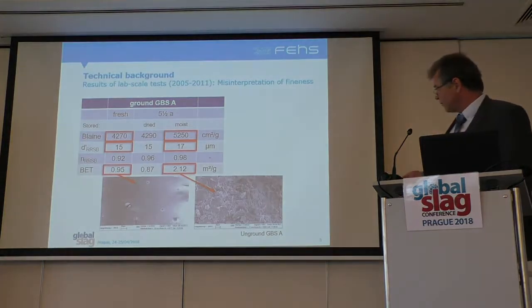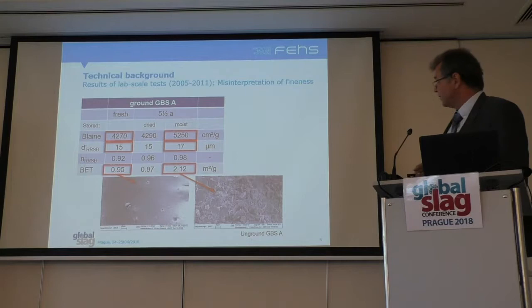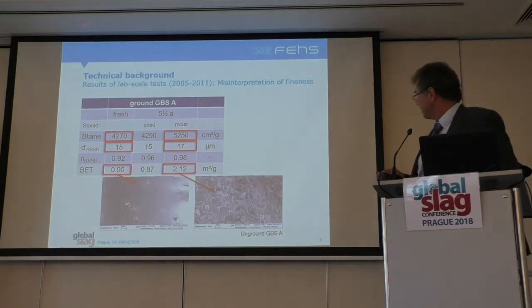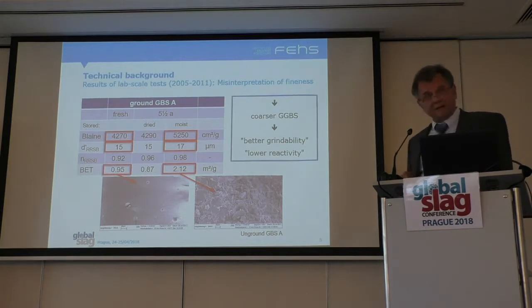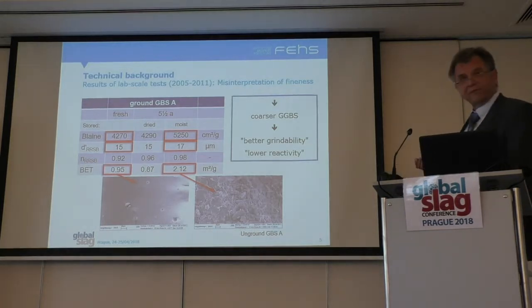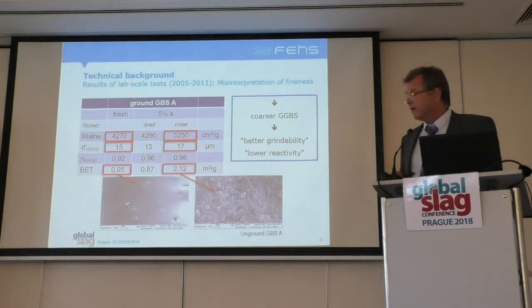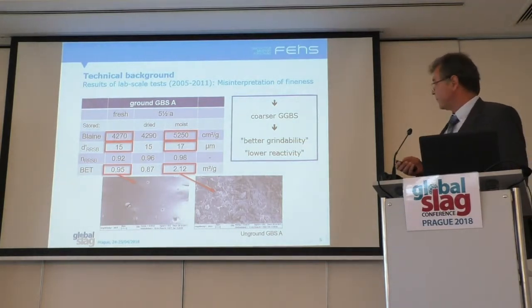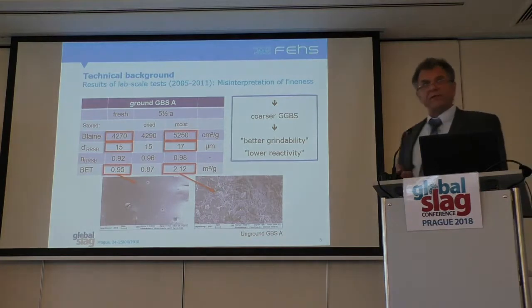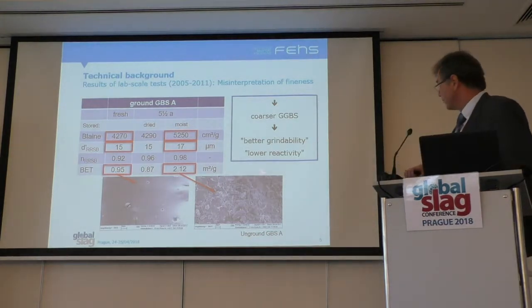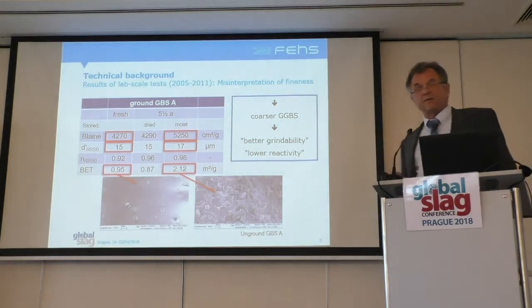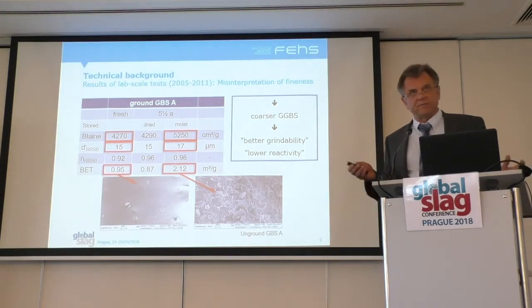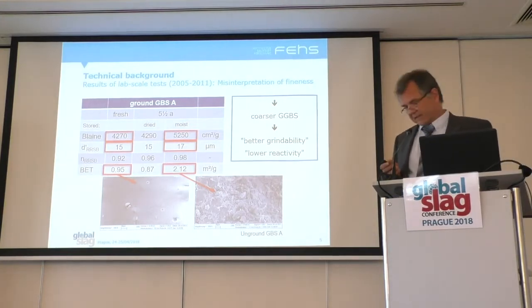That's a picture of the surfaces of unground slag: very smooth for fresh slag, and a reacted surface for the moist stored slag. The result is a misinterpretation of fineness. That means the slag, if it is ground GBS, is coarser than normal, than expected. So the feeling is you have a better grindability, but also you have a lower reactivity because, of course, a coarser material is less reactive. Very simple, based on lab scale tests.